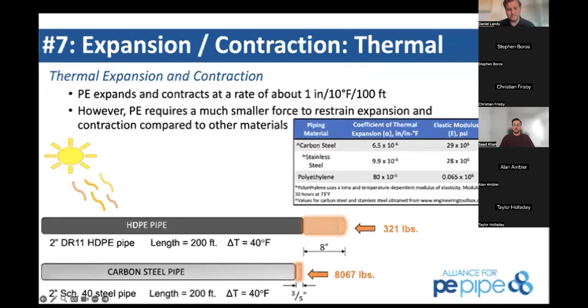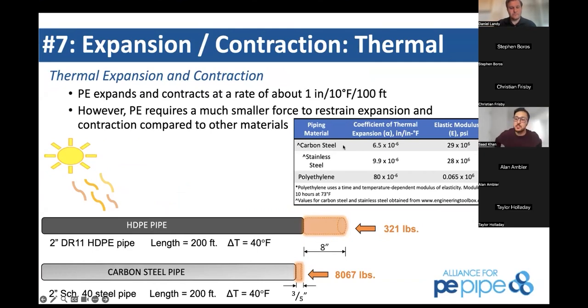Yeah. This is what we often get, perhaps one of the biggest scares that engineers display when it comes to specifying polyethylene pipe. And so this is a two-part piece of information. There are two characteristics that you want to be aware of when it comes to polyethylene pipes. Those two characteristics are your coefficient of thermal expansion, which is your middle column, and your elastic modulus, which is your right-hand side column. Now, polyethylene, for every delta temperature change for the same OD as, say, carbon steel pipe, is going to want to expand and contract more with every delta T. So if we take the example right here, for a length of 200 feet of 2-inch DR11 polyethylene pipe, for a delta T of about 40 degrees Fahrenheit, the polyethylene is going to want to expand about 8 inches, whereas the carbon steel pipe is only going to expand about 3/5 of an inch.